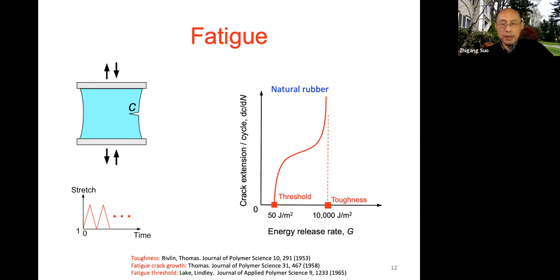This discovery has been standing there for all these decades until very recently. Natural rubber is fantastic, but if you make a cut, you can do this experiment yourself at home in the kitchen. Just do cyclic loading, and the crack will grow. The threshold is many orders of magnitude lower than the toughness under monotonic loading. This is also common experience for steel. If you have a bookbinder or pin, you just go back and forth several times, and the steel will break, right? So that's fatigue crack growth.